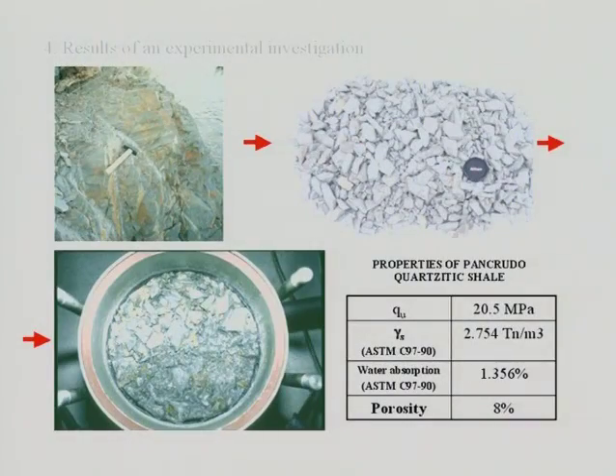What we did a few years ago was to select a quarry. Actually, there is a dam that is being built out of this material. The work is now started. And so we crushed material, and we prepared a gravel, and we tested it under oedometer conditions. The material is a quartzitic shale, and it's a relatively good material. This is the unconfined compression strength. It's like a relatively bad concrete, but it's not bad in general for a shale.